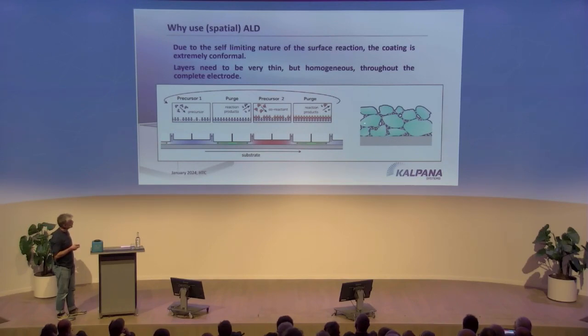Now, if you want to go to high speeds with ALD, you cannot separate the ALD steps in time. You can separate them in space, and you have spatial ALD, and you would end up with a deposition head, something like this. And you can do ALD faster, but you end up with a few new challenges. One of them is, of course, keeping the gases separated. They're all present at the same time, and it's very challenging to keep them separated.